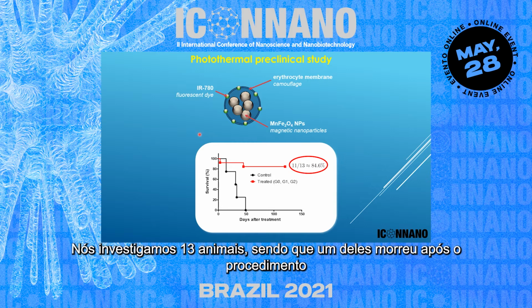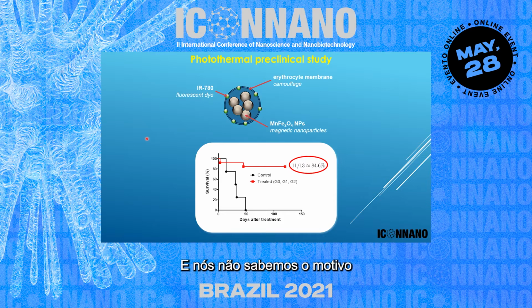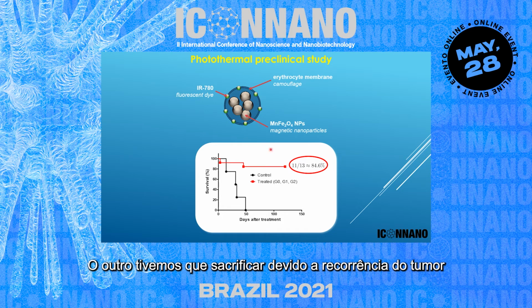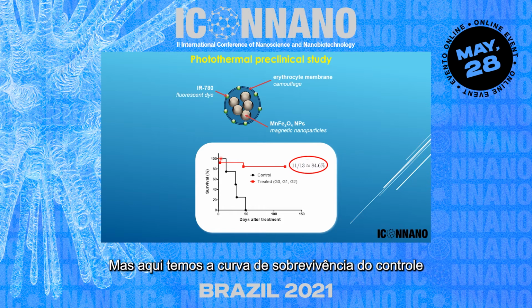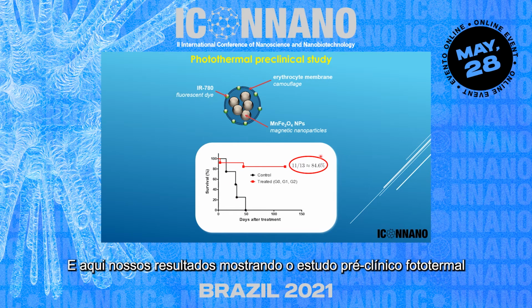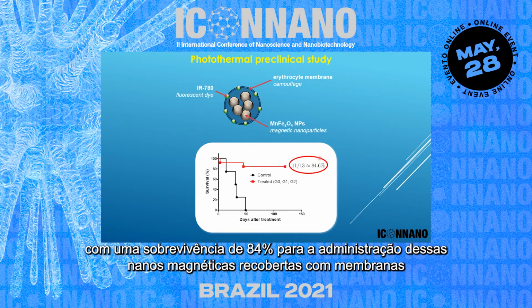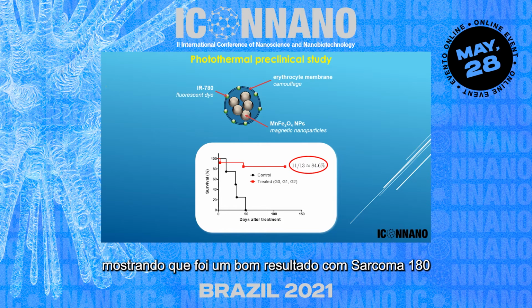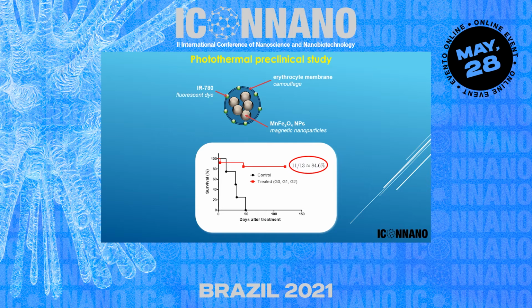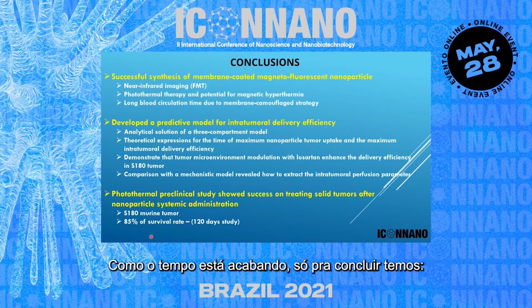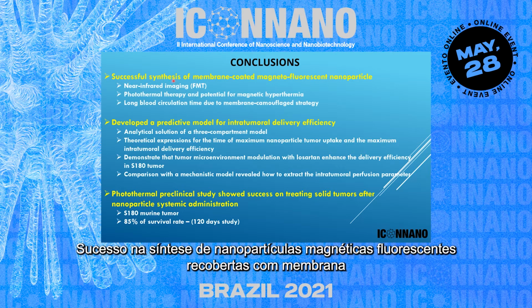So we investigated 13 animals. One of the animals actually died after the procedure. We don't know the reason why. Another animal we had to sacrifice because of tumor recurrence. But this is the Kaplan-Meier curve of the control, and this is our results here showing that the photothermal preclinical study after administration has an 85% of survival for this membrane camouflage magnetic nanoparticle, which is very, very good for sarcoma 180. I just noticed that I'm almost out of time, so in conclusion, very fast, we had successfully synthesized